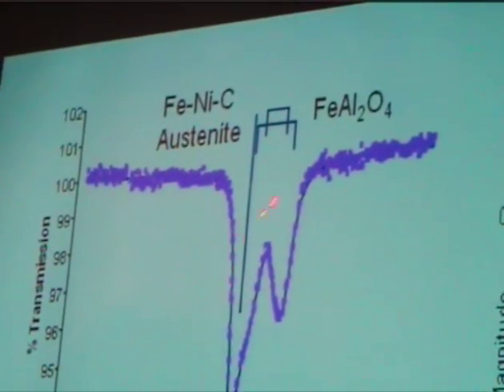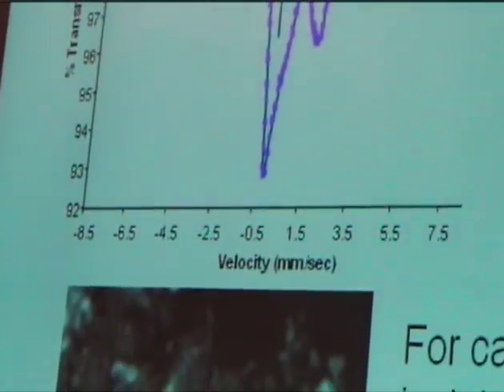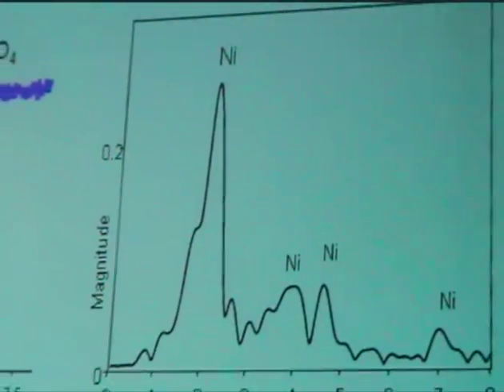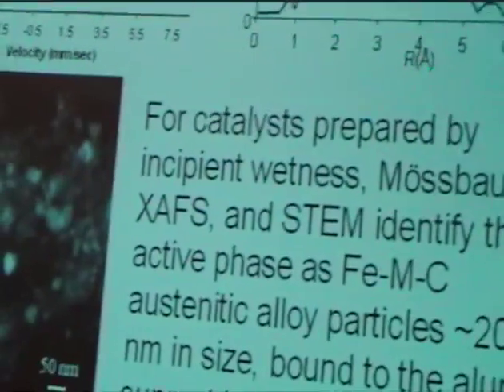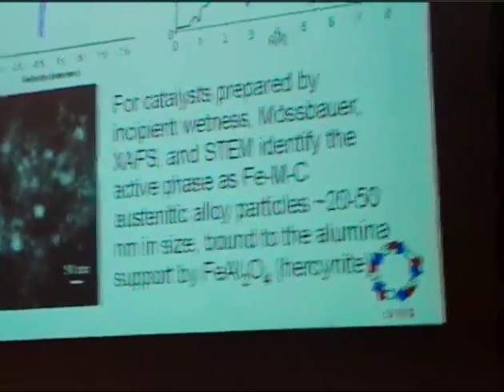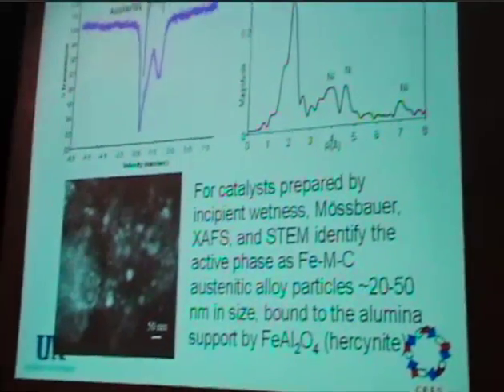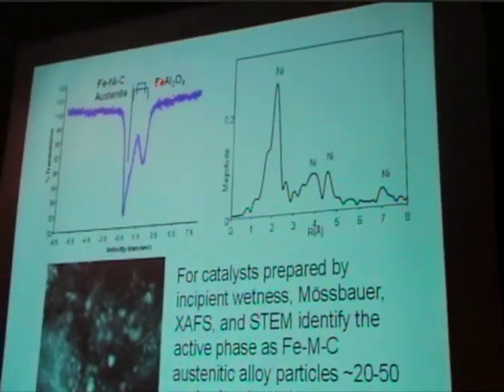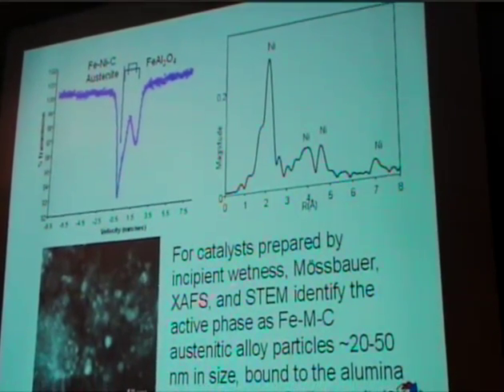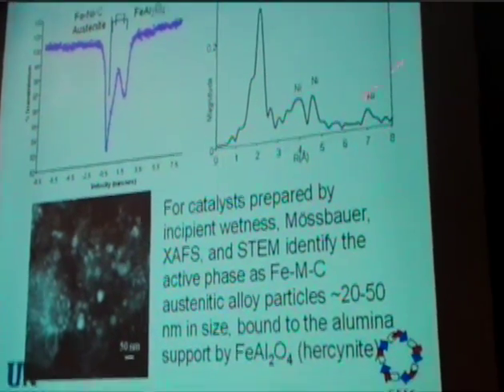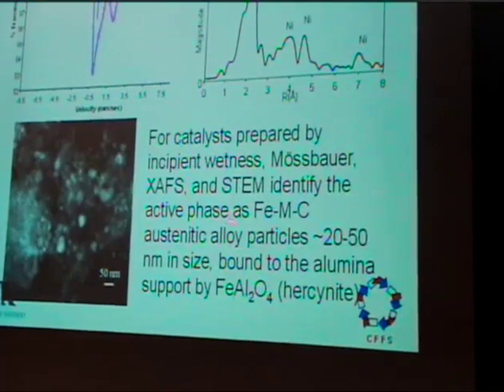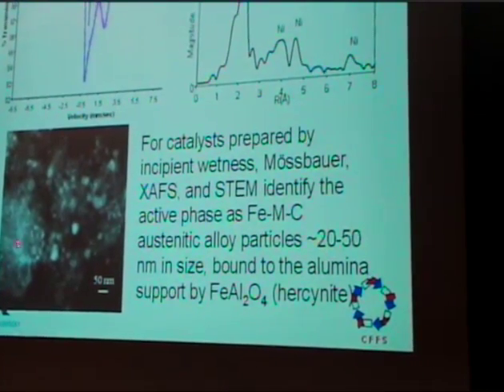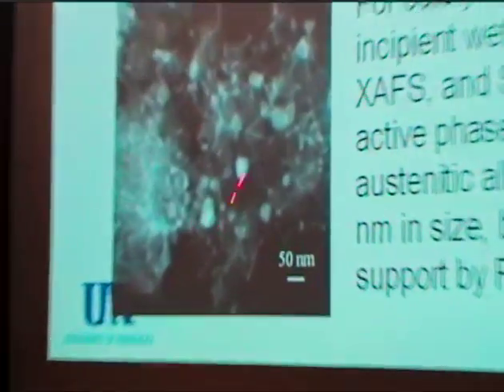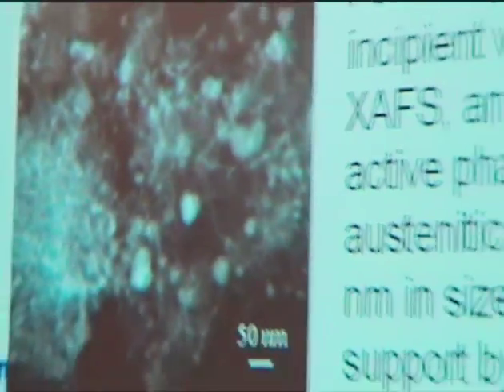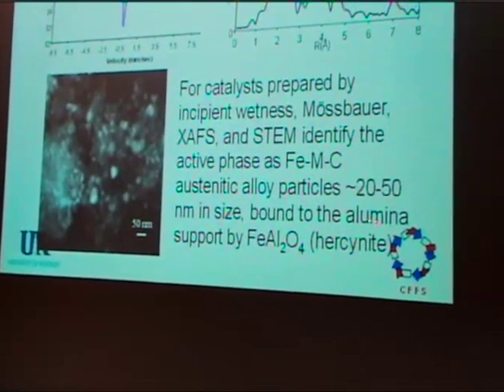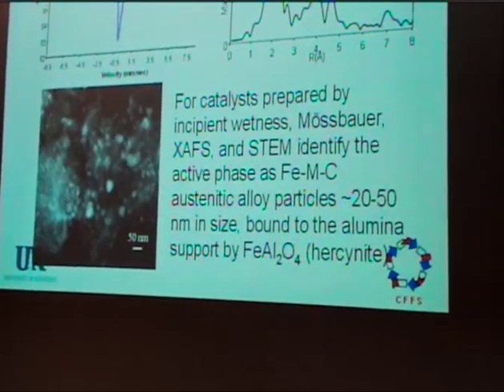To determine the active phase, we like to use Mossbauer spectroscopy and XAFS spectroscopy. And it is indeed an iron nickel carbon austenitic alloy. It is a face-centered alloy that contains carbon. And we also see a significant amount of a secondary phase called hercynite, which is an iron aluminate. And for catalysts prepared by incipient wetness, which all of these were, we find that the particle sizes are about 20 to 50 nanometers in size on average, and you can see them scattered all around on the aluminum support. And the particles, in fact, turn out to be bound to this support very strongly by that hercynite phase.